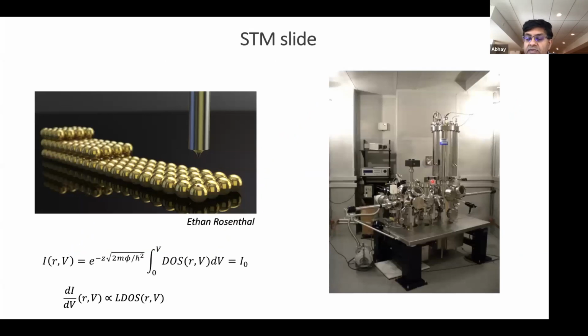So the initial part of the experiments that I'm going to show you are all coming from STM. This is my one slide on STM for the uninitiated. STM has a metal tip on top of a surface with tunneling happening between the tip and the surface. And the number of ways you can have tunneling between the tip and surface is proportional to the density of states, the number of available states at that particular point. So it's a good way of measuring the local density of states at a given point in space and at a given energy.